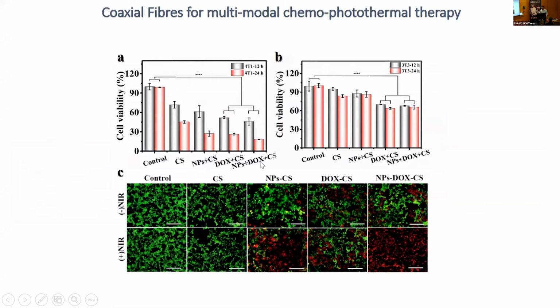Basically, it showed that after we did the simultaneous dual therapy with doxorubicin and with the nanoparticles, we got the most therapeutic efficacy. We also saw some negative effect of the core shell fibers alone by themselves. But interestingly enough, when we tested them on healthy fibroblast cells, we didn't see that effect. So we hypothesized that this could be associated with anti-cancer properties of the dopamine molecule itself.